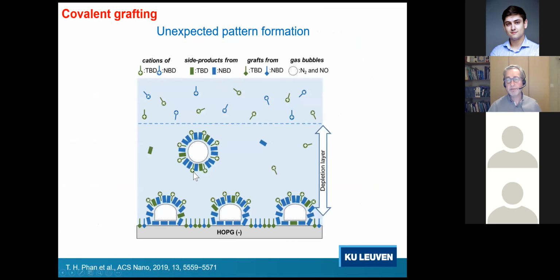And we believe that the reason we have some areas which are not grafted is due to gas bubbles that are formed and adsorbed on the surface while we are exposing the substrate to the reactive radicals.